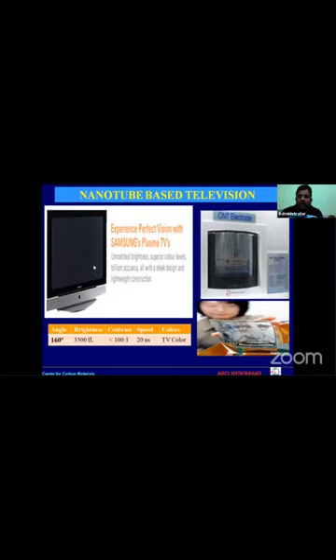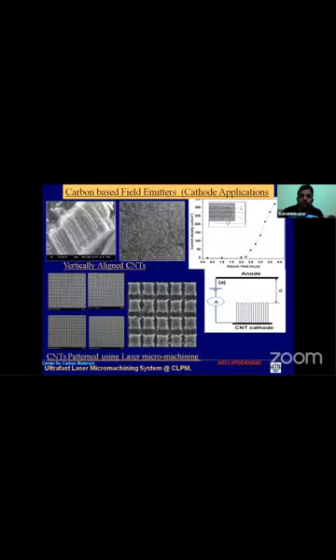Now people are talking about giving a coating of carbon paste on a plastic sheet, so even a flexible TV one can get. So we have developed aligned carbon nanotube cathodes. But what happens, the edge carbon always gives a very strong field emission effect. So we have given a pattern to the carbon nanotube jungle. This was all a complete jungle, but we have a very strong laser center. We have used the laser energy to make a different type of pattern. This is a magnified view of that. So the onset of emission has decreased drastically. This is a project we have done for DRDO.